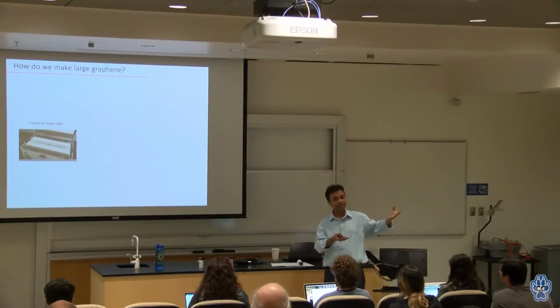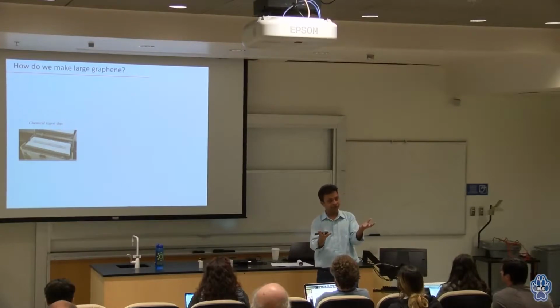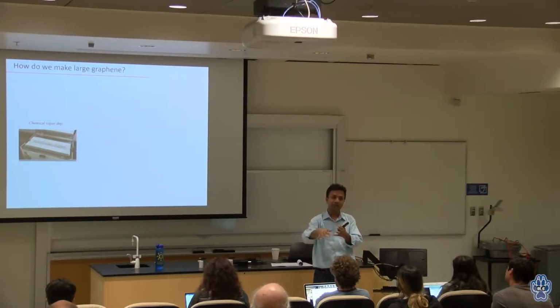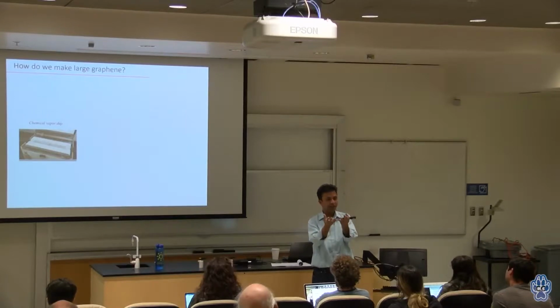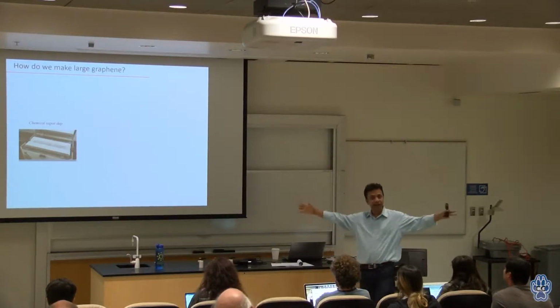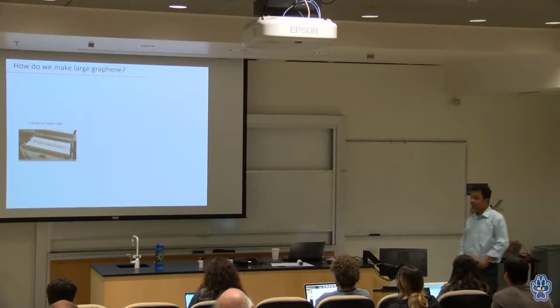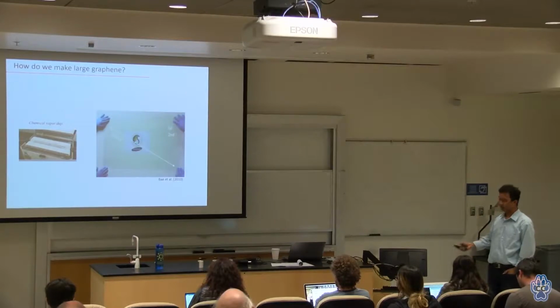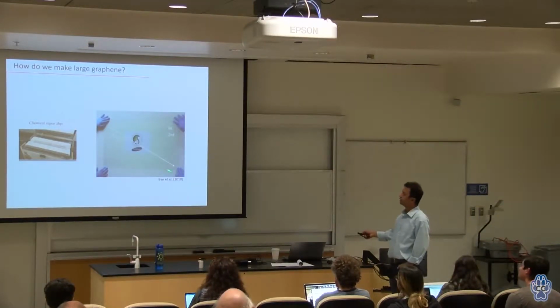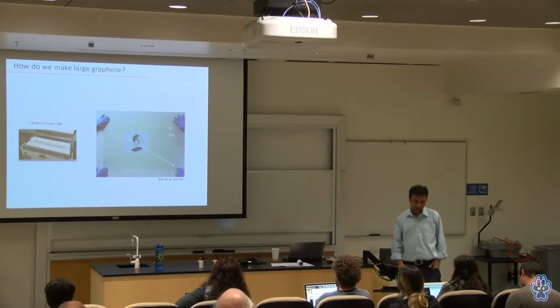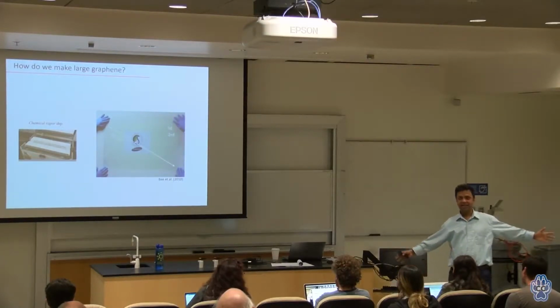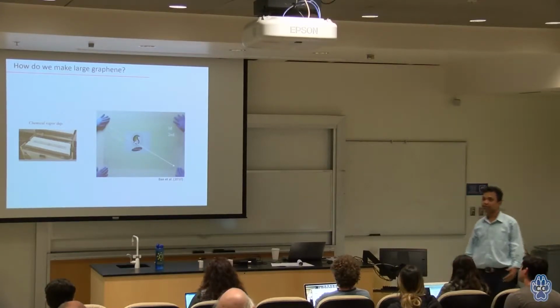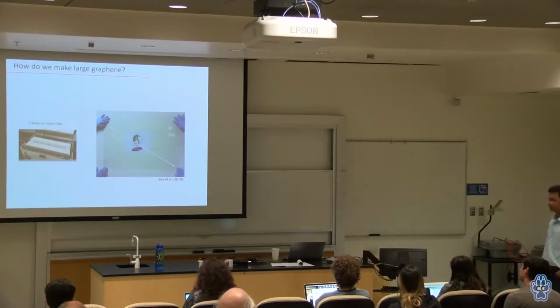In my lab, we put copper foil, and then we inject methane gas and hydrogen gas. We ramp up the temperature to 1000 degrees centigrade. The methane breaks up, and methane has carbon in it. Those carbon atoms get into the copper, and then when you cool down very quickly, those carbon atoms get to the surface, make those bonds, and make a large graphene sheet as large as your copper plate. For example, this is made by a Korean group with Samsung. This is almost 30 inches, and the current record is by Sony. I think it is 100 meters long and 2 meters wide. So people can really scale up this technology to make 1 atom thick materials for your technological applications.